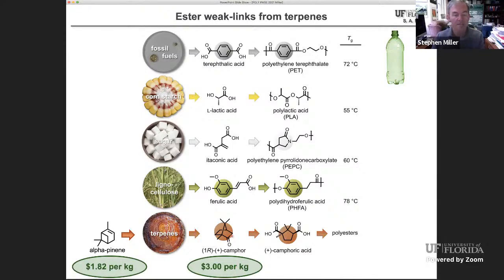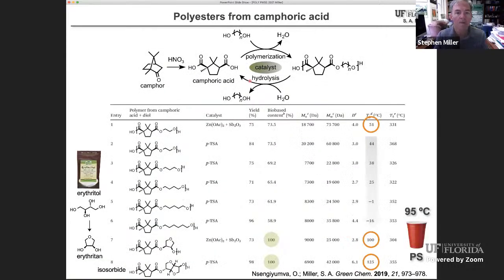We and others can oxidize camphor with nitric acid to camphoric acid. And so now you have a diacid, which of course looks like something very interesting to a polymer chemist. And we have made a variety of polyesters from this. In our first studies, we simply copolymerized camphoric acid with a variety of alpha omega aliphatic diols. With ethylene glycol itself, you get a Tg of about 51 degrees. Again, very similar to the Tg of polylactic acid. If you use longer diols, you just have lower glass transition temperatures, probably less useful as a packaging plastic.